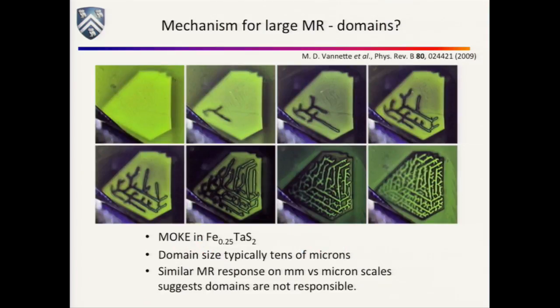Sorry, I should have explained. This is cranking up the magnetic field and getting closer and closer to the coercive field. This is the magneto-optic response. So you're basically breaking the system up into domains, and at some point you really coerce everybody. If you kept going, this whole thing would turn black.